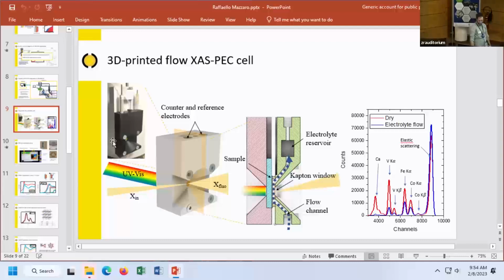Now, the cell design was thought out in order to have an electrolyte layer on the surface of the photoelectrode that is as thin as possible, as we basically need to work in fluorescence. So we need to minimize the attenuation from the electrolyte itself, and also we have to have a thin window. So we work with a Kapton window.